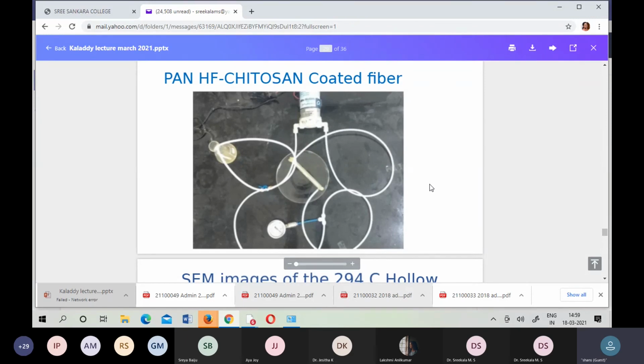Because this hollow fiber coating is a little tedious. When you have a flat sheet membrane, you put it on a glass plate, put sellotape and make it flat, and we do dip coating or spray coating. But in the case of hollow fiber, we have to do dip coating, but we don't have enough chitosan solution. So we stick the hollow fibers on our glass plate, prepare the solution, and dip them inside. The first picture shows how we did the coating. The second one is the glass flow unit, where we made the module. This is a small module we made, with an inlet and an outlet.